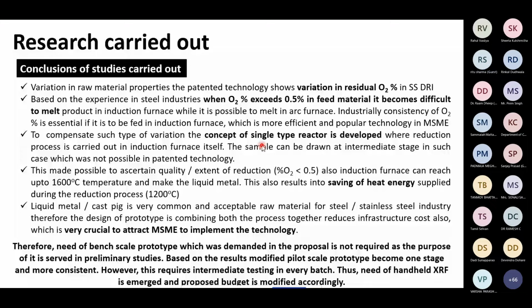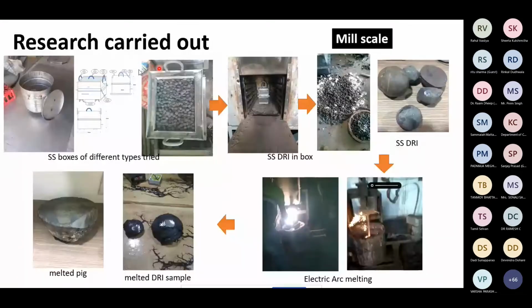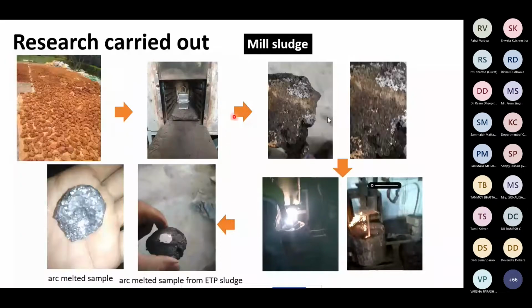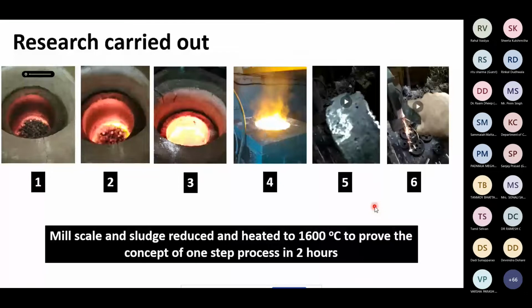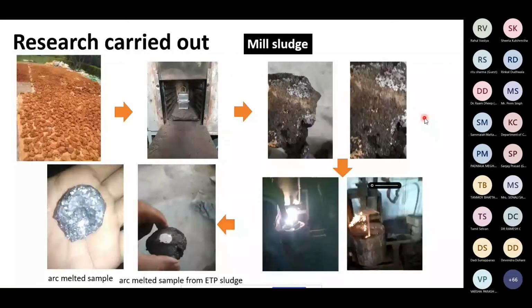So in summary, in conclusion, the need of the bench scale prototype which was demanded can be met. So here is a bench scale reactor, which is further used for the sludge also. But here we need to go for the two-step process. The first step is over here, the second step is over here. Now this two-step process can be reduced to a single step also if the proper fluxes are introduced. So in one furnace only we can directly get the final reduced metal from the scale and sludge. That is what our target is, and studies are going on. Whatever demand is there, a two-step process is required, but we can prove that one single step process is also sufficient.